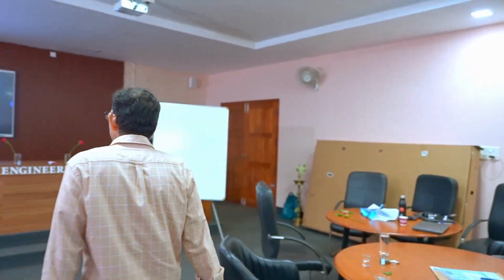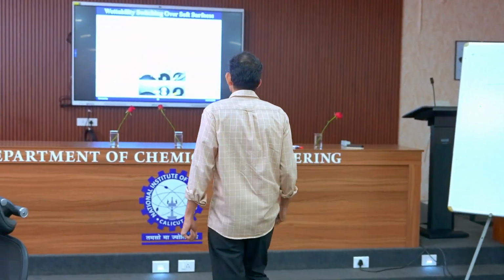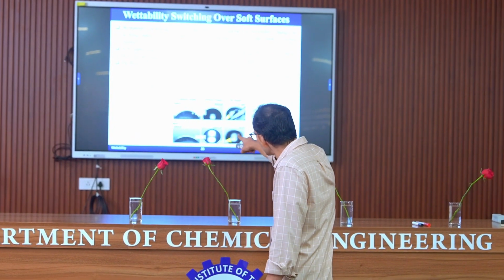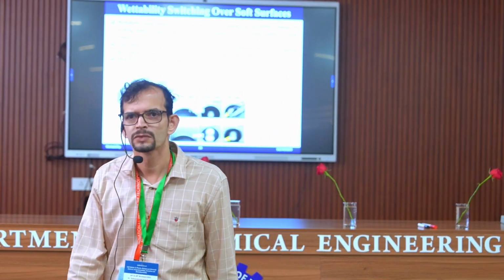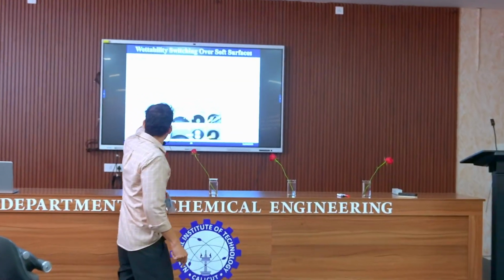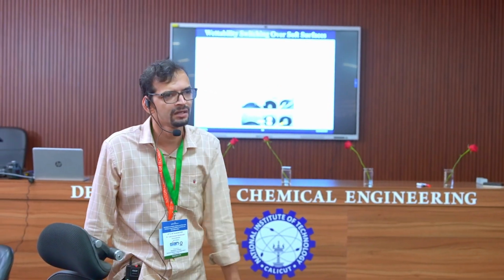you can realize this gradient. We started that experiment in 2016, and we started with the PDMS layer, the first one. You can see at two temperatures, the first one is lower and the second one should be higher. Banu? Yes, while cropping we missed that. Okay, no problem. So on the left is a low temperature, something like room temperature. The right is 40 degrees, for example. You see there is a contact angle increase, because it becomes more of an enemy of water.